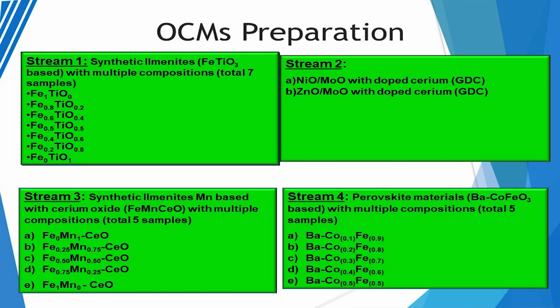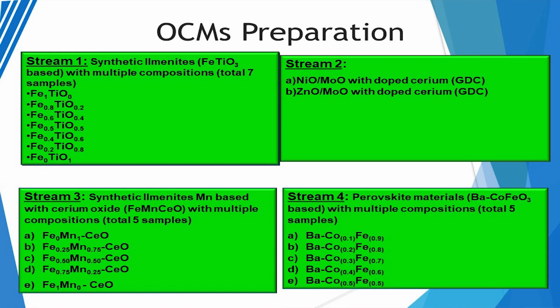The confirmatory tests are how we can test this redox cycle for the material: whether it is stable, or whether it gives more oxygen carrier capacity, and how that can be calculated from the system. TG is the best tool, because the air and fuel reactor works at more than 800, 900 degrees. Here we have used one material with a 50-50% ratio of iron and titanium. Titanium can also stabilize the iron phase. First we checked in syngas fuel and then in methane. Methane is very stable, but the oxygen transfer capacity in syngas is very good, because in methane there is some carbon deposition on the material and then some agglomeration during the process. There are a lot of challenges and problems, but it can be catalyzed with a different catalyst material.